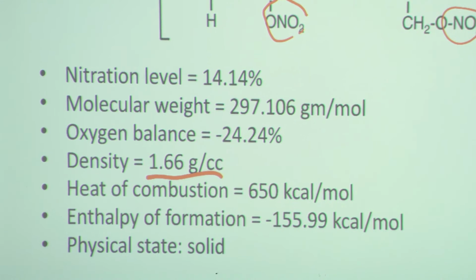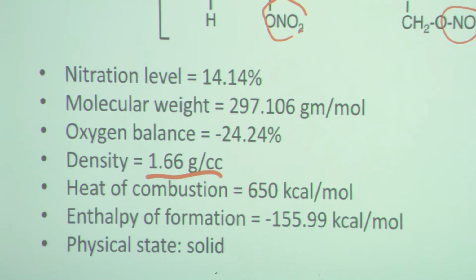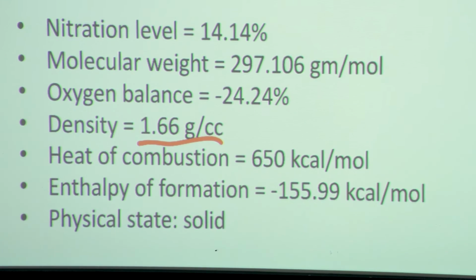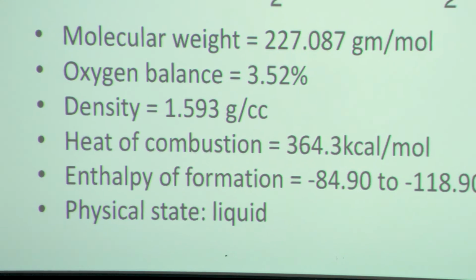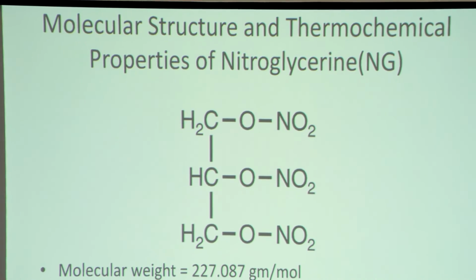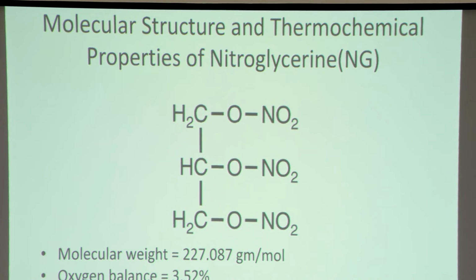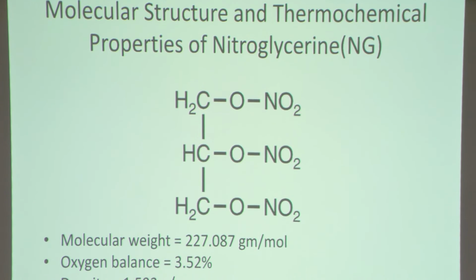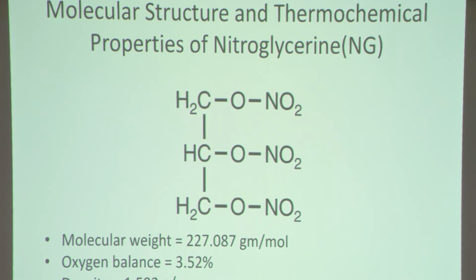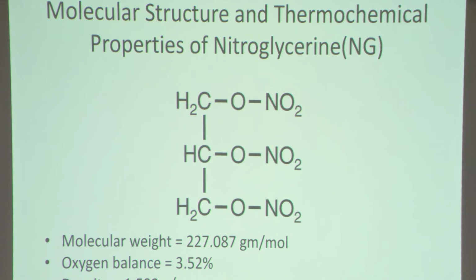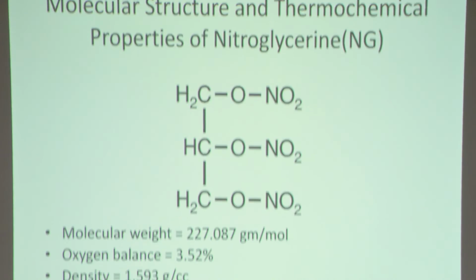Density, very important, 1.66. Okay, if I look at something like a liquid hydrocarbon or even HTPB, the densities are going to be probably a little less than 1 gram per cc. So here you can see in this structure, I'm getting a higher density than I'd get out of something like a typical hydrocarbon fuel. Heat of combustion, 650 kilocalories per mole, enthalpy of formation, minus 156, and the physical state is a solid. If I compare that now to nitroglycerin, it has a structure shown here. So you can see it's a linear chain of basically carbon with hydrogen off it, and off of the carbon atoms, I pulled off an H atom, and I put a nitrate group, an ONO2 group, on each of the carbons. Okay, without going into all the details, you can see it's a liquid versus the solid that nitrocellulose was.